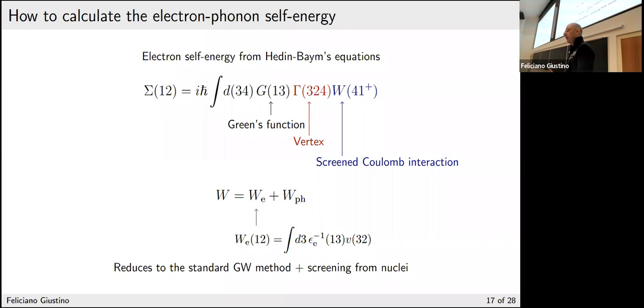So in fact, there's been some discussion in the literature. People say, okay, why don't we use directly the complete dielectric matrix to do these things? So we get rid of electron-phonon interaction, we bundle them up with GW methods, and we're done. So there is a complexity with that, because typically the energy scales and the k-point sampling required for these two problems are very different, okay? So you cannot just lump them all together, because the accuracy needed for one is not the same as for the other. So typically it is better to separate them, and handle them in two separate chunks.